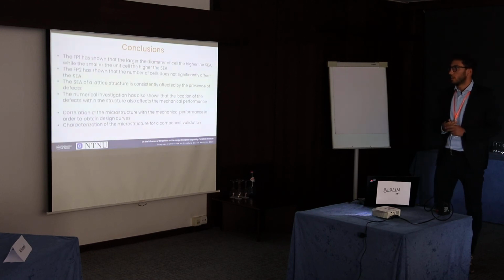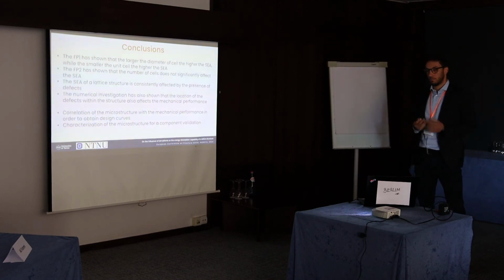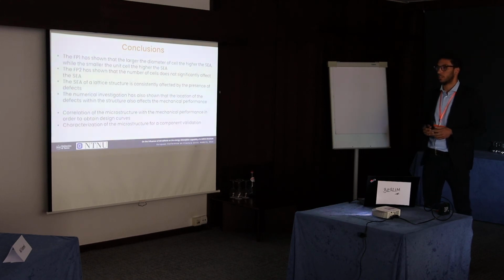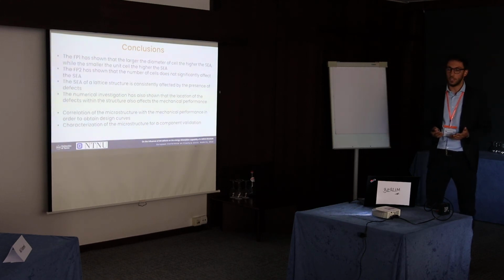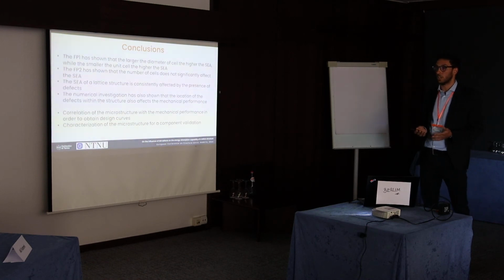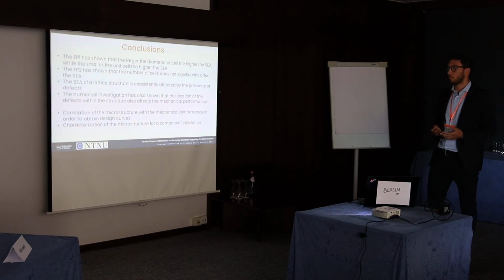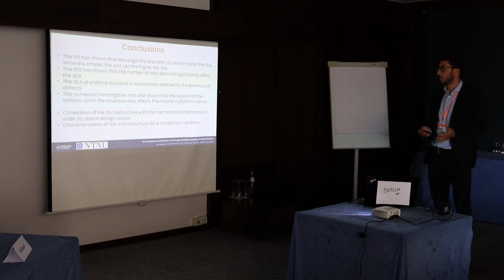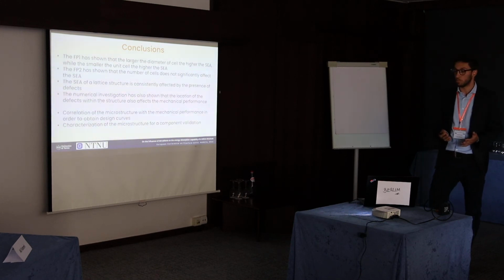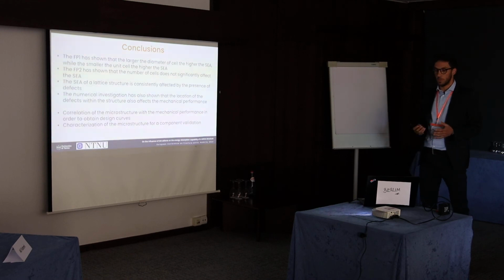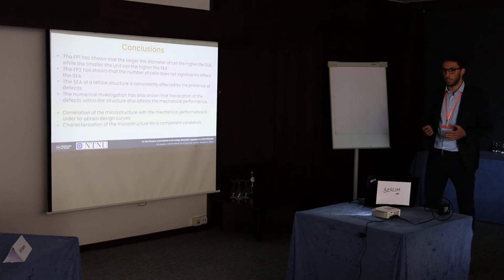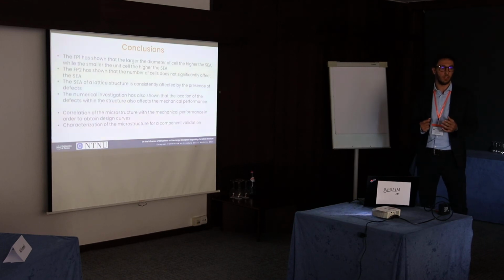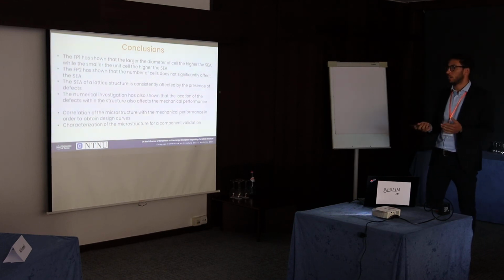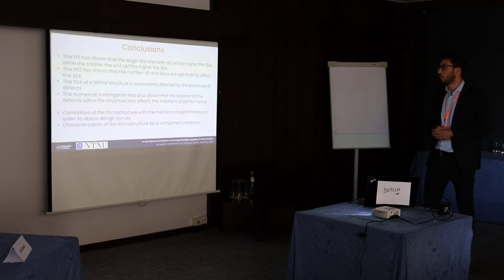So in conclusion, the experimental campaign has shown that the larger the cell diameter, the larger the specific energy absorption, and also that the number of cells does not significantly affect the specific energy absorption, which means that we can evaluate the specific energy absorption of a unit cell on specimens made of small replications, and then use that result in the design of a component.